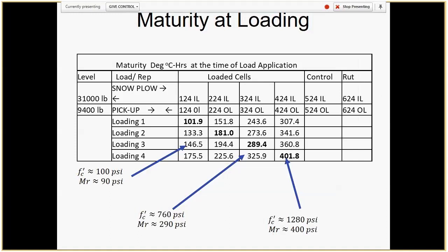And basically, that analysis was already conducted by MnDOT, but we went back and double checked it and slightly corrected it. But basically, what we say is that the third loading of cell 124 corresponds to about compressive strength 100 psi and modulus of rupture 90 psi. So because it's a maturity about 150, and fourth loading of cell 324, the compressive strength was 760 psi, which is quite low, but the flexural strength was already almost 300 psi,